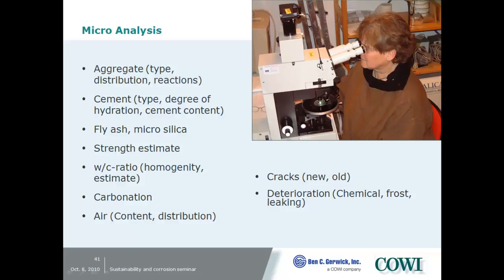In the microanalysis we can look at the aggregate type, distribution, any reactions that would take place, the cement type, degree of hydration, cement content, whether fly ash and microsilica have been used, and how much. It's qualitative, not quantifiable; it's difficult to quantify in a microscope.